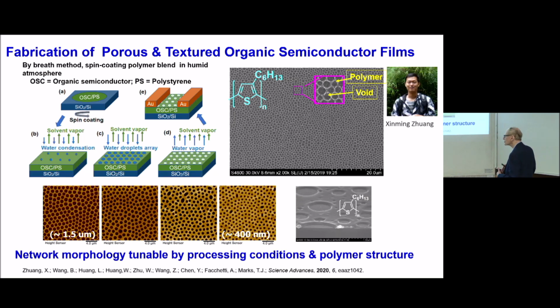So this has been in the literature for a long time, but nobody really thought of doing this. But as I make a solution of an organic polymer, and the organic solvent slowly evaporates, if I do this under a very high humidity atmosphere, the water stays, and the water droplets organize, and when it's all finished, I have a material with holes in it. So it's porous, and we can tell that it goes all the way down to the electrode here.